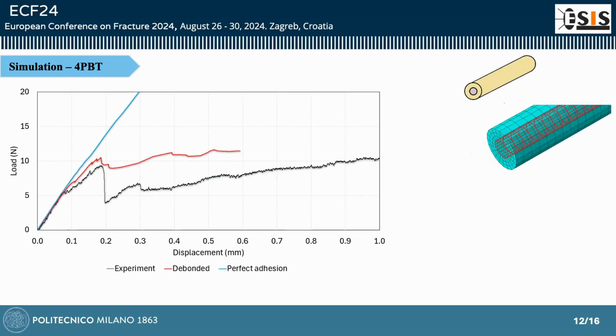In this slide, one of the most important points in the composite filament is the contribution that the core and the shell together are going to add to these specimens. And we wanted to check what would happen if we use a perfect adhesion simulated model and a debonded one. And here we were able to capture the first drop by using the debonded model. Although we know that for capturing the next peaks, we need to work on that, but at least we can say that a perfect adhesion model is not going to simulate such models well.